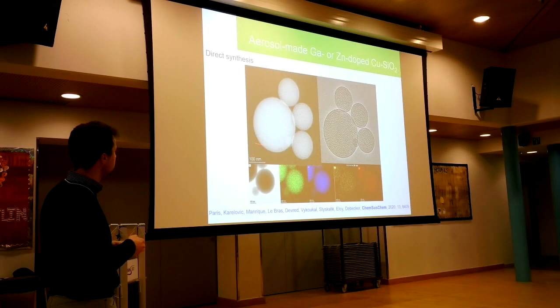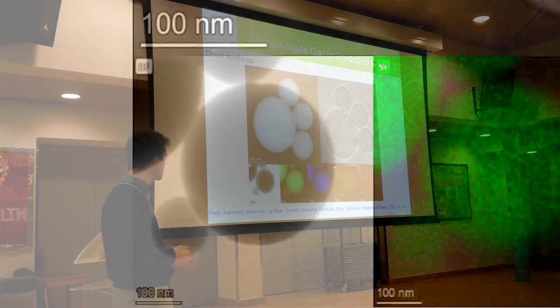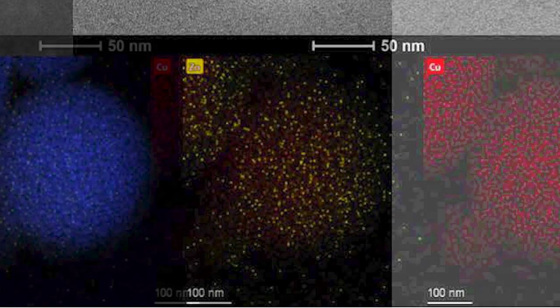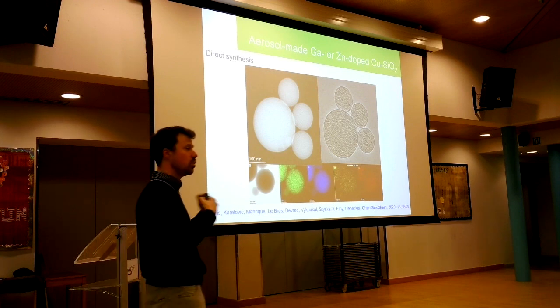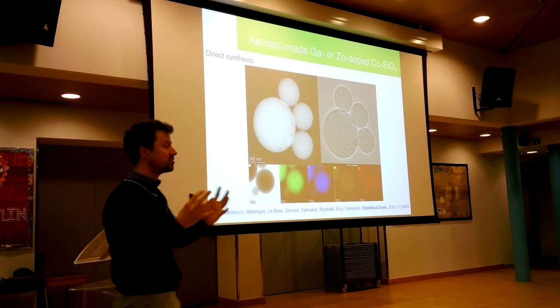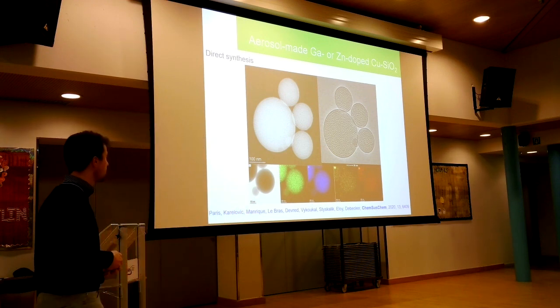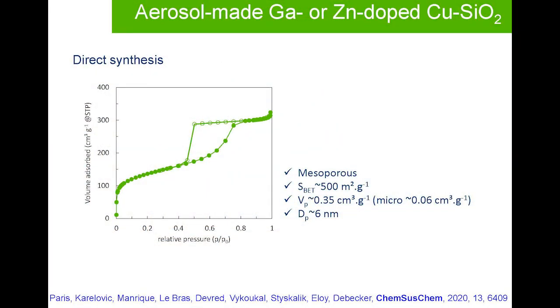So kind of nice spheres, porous. If you look at the elemental mapping, of course you get silicon, oxygen, the dopant, in this case zinc, and then you can see that the copper is very dispersed. This is something that we want in catalysis. We don't want big chunks of copper, we want dispersed copper. So that's quite nice. I told you in catalysis also we need pores.